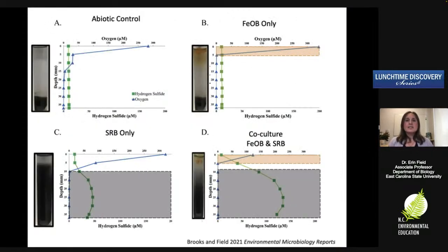And what you can see here, each of these gradient tubes you just saw, we have the orange where the iron oxidizers were, and then we have the black where the sulfate reducers were. And to confirm what I was just saying, the iron oxidizers grow until oxygen disappears. Sulfate reducers grow until oxygen shows up. But when you grow them together, they leave this zone of clearing. And the sulfate reducer doesn't grow all the way to that oxygen barrier, where that five is.